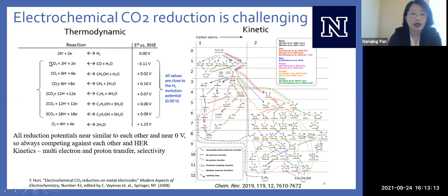And if we look at all these reactions for the CO2 reduction reaction, generating carbon monoxide or methanol, methane, ethylene, these values are also very close to 0. Not only are they close to 0, they're really close to each other. And so what this means is that all these CO2 reduction reactions are not only competing against the hydrogen evolution reaction, they're all competing against each other.